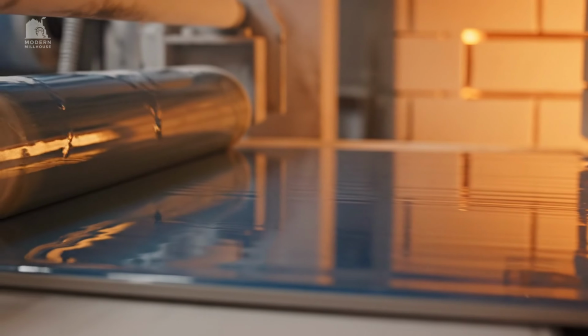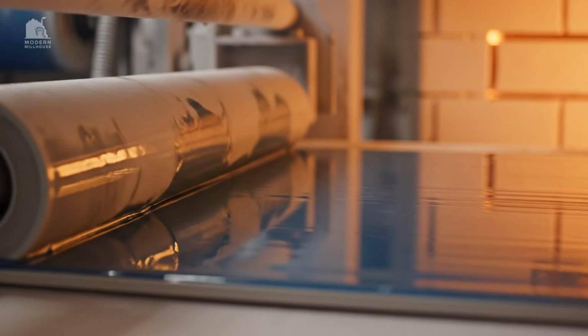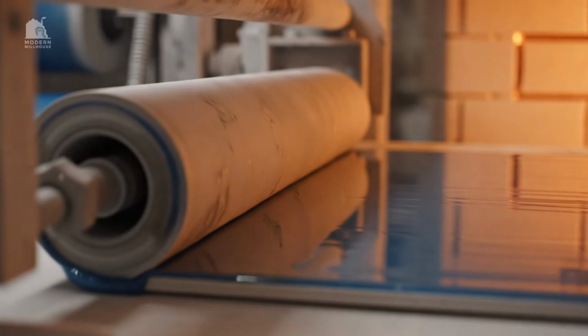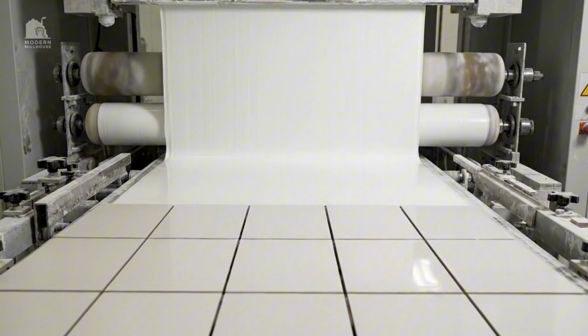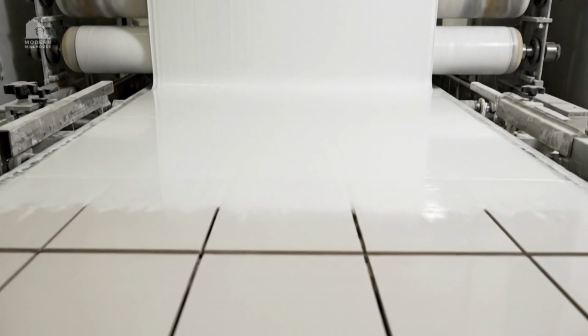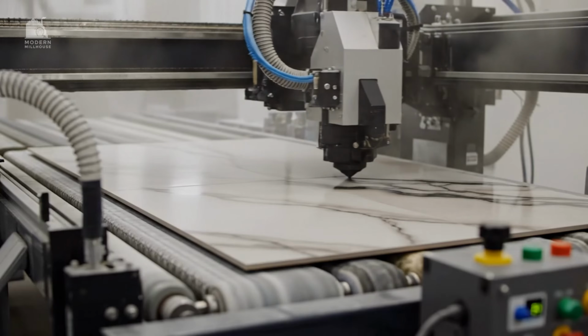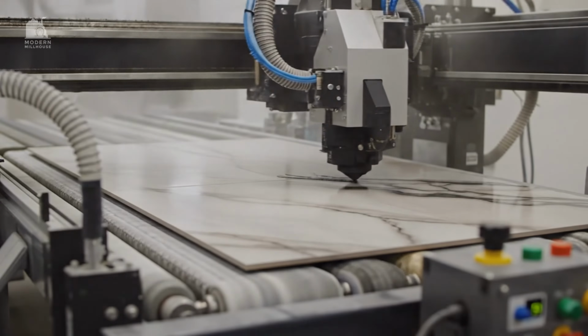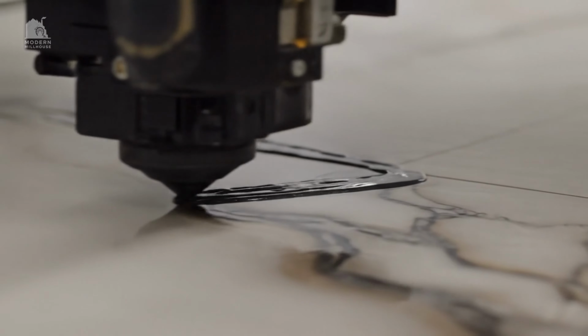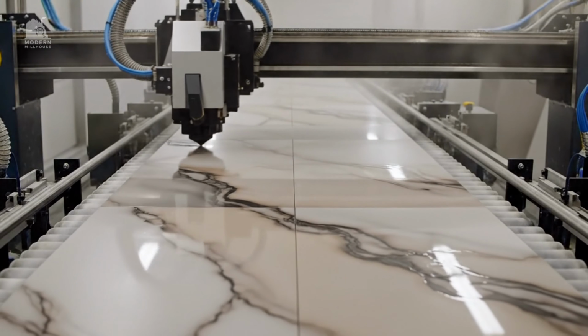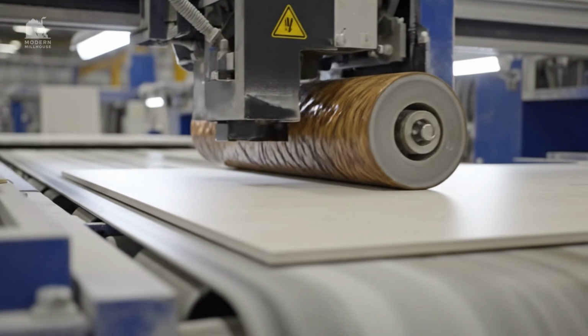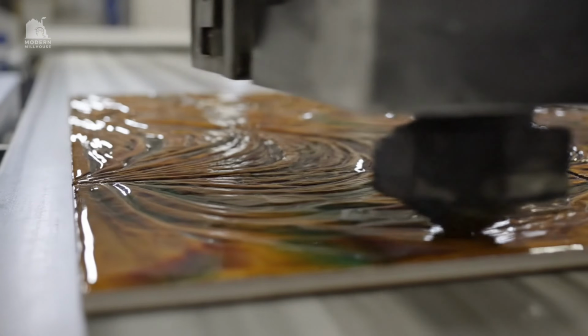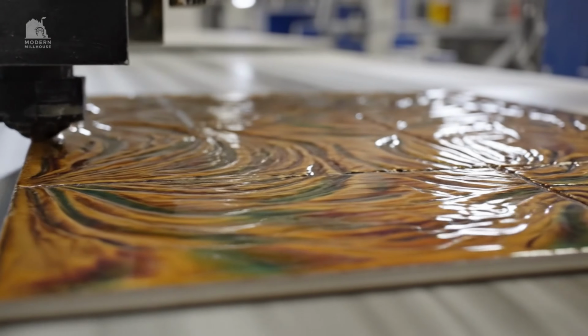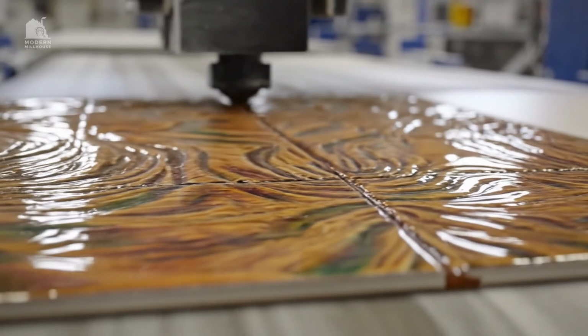A glaze that melts too easily may flow beautifully but scratch more easily. A glaze that is too stiff may resist scratches but show orange peel texture or incomplete leveling. Matte glazes often rely on microcrystals or controlled surface roughness, which must be tuned carefully. For glossy tiles, the challenge is avoiding bubbles and pinholes while achieving mirror-like smoothness. Color control is a major part of glazing.